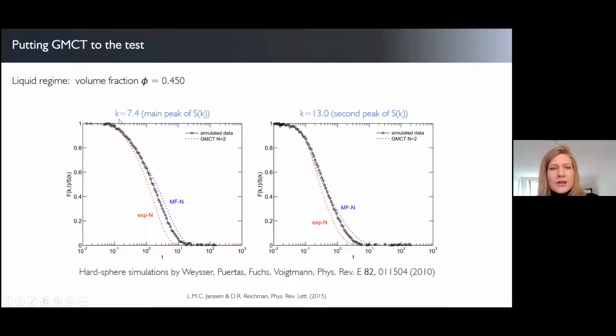Now these two plots here are still for fairly low volume fractions where the system still behaves as a liquid. And so this blue dashed line here is a standard mode coupling result. And you can see that it's not far off from the real result from the simulation. But if we go to a higher order in generalized mode coupling theory, we get slightly closer to the exact result. And the highest order I could calculate at the time, so making a closure approximation at the level of 8-point correlation functions, gets us almost exactly to the result that it should be.